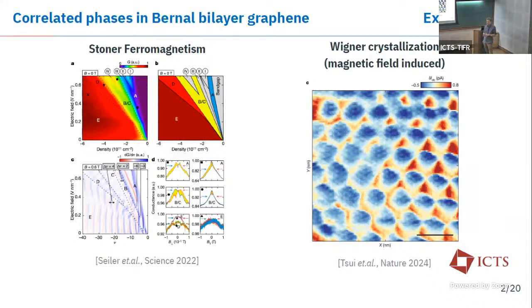has emerged as a very interesting material in the last couple of years because starting in 2022, people have actually measured and cartographed, so to say, different strongly correlated states in that material. It started with the observation of ferromagnetism in both the valley and spin degrees of freedom in certain very low hole doping regimes of Bernal bilayer graphene under a transversal electric field. That electric field breaks inversion symmetry of the material and therefore creates some Lifshitz transitions, some van Hove singularities, and it is believed that some of these instabilities could actually be weak coupling driven electronic instabilities.